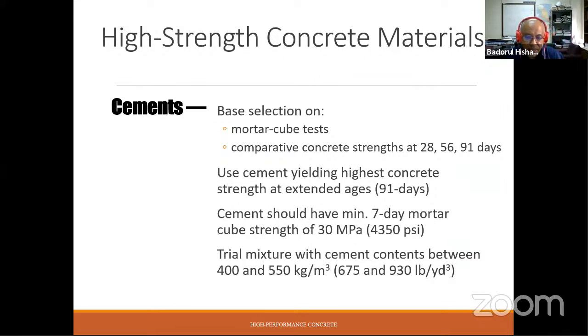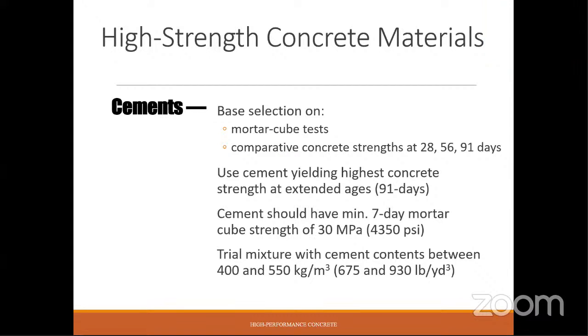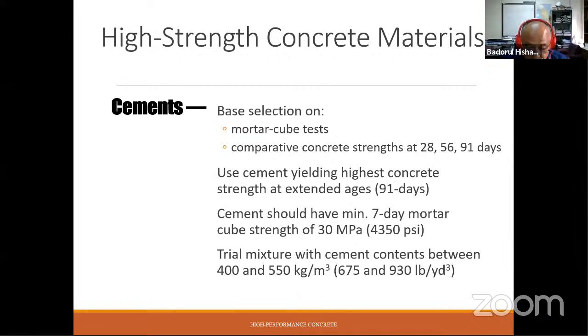Cement. The physical and chemical characteristics of cement play a vital role in developing strength and controlling rheology of fresh concrete. Basically, the fineness of the cement affects the water requirement for consistency, for example. When we look for the cement to be used in high performance concrete, one should choose cement containing as little C3A as possible, because the lower the amount of C3A, the easier to control the rheology, or the lesser the problem of cement superplasticizer compatibility. So finally, from the strength point of view, this cement should be finely ground and contain a fair amount of C3S.